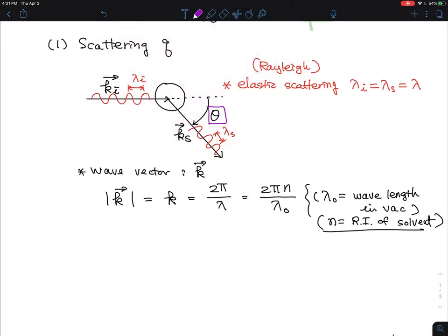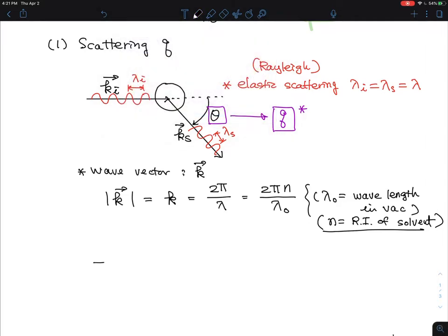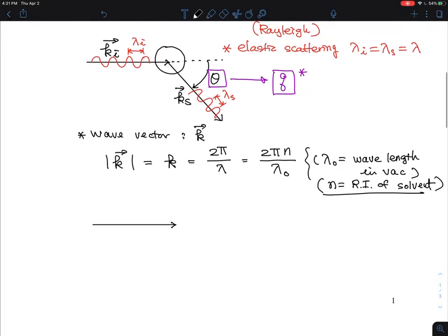Okay, this is a scattering theta into something called a Q. Scattering Q. And how I'm going to do it is, let me draw the new schematic diagram. So here I am going to just draw the same scenario, and then this is a wave vector that has the same length. Their length K is essentially 2 pi over lambda, as has been defined, and then this is an extension of the transmittance line. That is a theta that is shown up here.